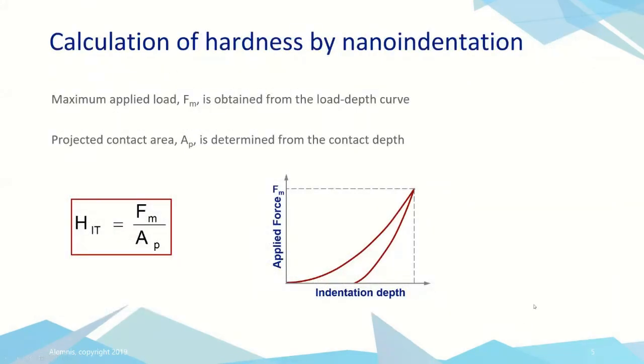Now, the way we do that is exactly the same theory as conventional indentation. So what is hardness? It's basically load divided by contact area, which is pressure. And we do this exactly the same way at the nanoscale. So from our curve, we know FM, which is the applied load, because we've set it in the software. And the contact area, AP, or the projected contact area in this theory, is taken directly from the calibration of our indenter shape. Typically, we might be using a three-sided pyramid, a Berkovich-shaped indenter, and so we know the area at every depth that it might be used at, and we use that calibration curve to understand what is AP at the contact depth that we're using.